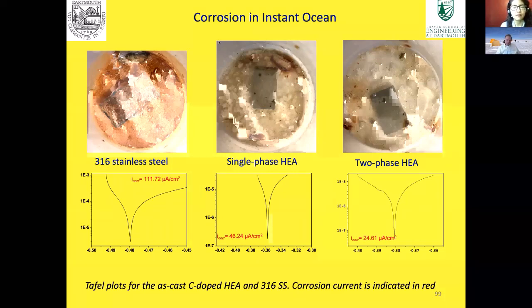Actually, I should say I am not an expert on corrosion at all. I did these things by just simply sticking some specimens in solution. One of our other faculty members here actually had one of their graduate students do these actual measurements. They're a corrosion expert. So I really don't know the answer to your question. And as I mentioned before, the comparison with stainless steel is because we put this in this material, instant ocean, which has chlorides in it, so it would attack stainless steel, which is not good in a chloride environment. So I think that's a good question, actually. This single phase alloy is actually worse than the two-phase alloy, which is sort of interesting. So this is sort of backwards from what you might think, actually. This is a B2 and FCC, and this is just FCC.